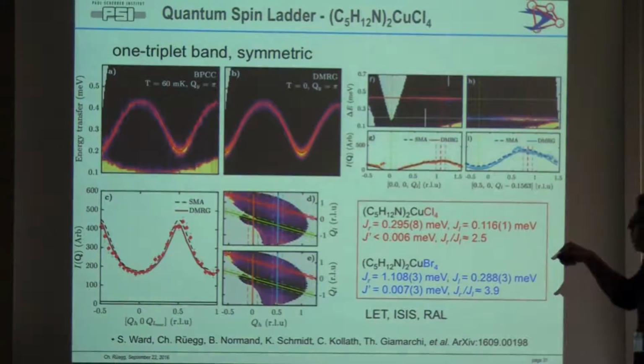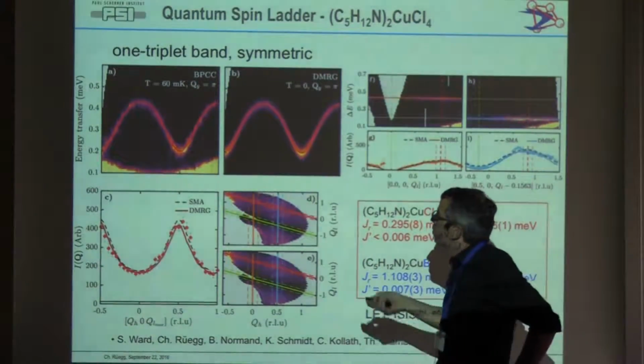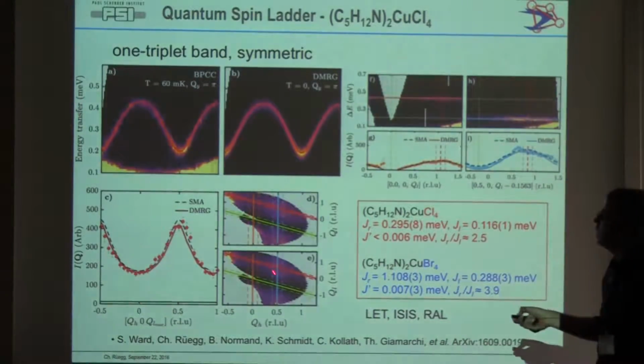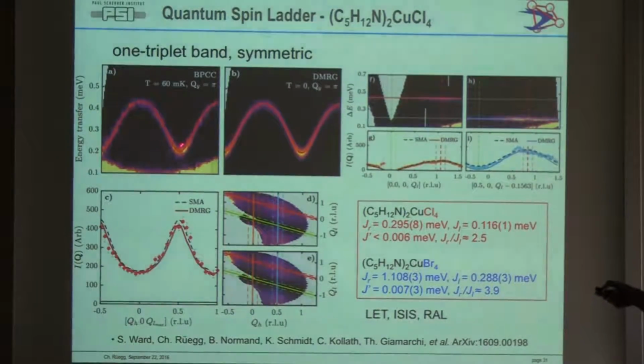Okay, then you cut into several directions. You want to know what's the dispersion in the ladder direction. Here on top you see that. On the left you see beautifully this magnon band. This is now the chloride material. The gap is 0.2 meV. The bandwidth is also 0.2 meV. If you cut it in the other perpendicular directions, you would see no dispersion at all. So this is really a beautiful 1D material.